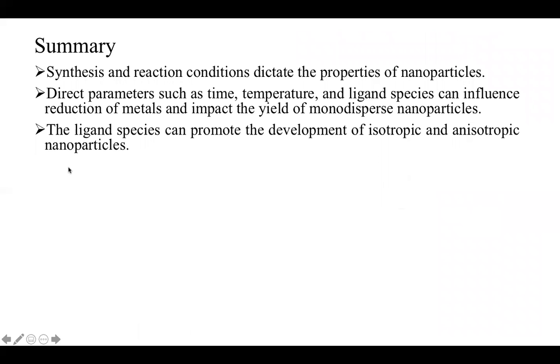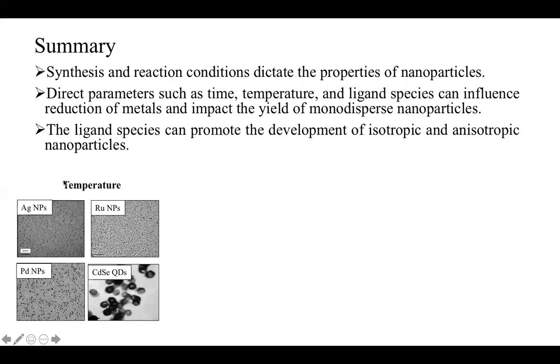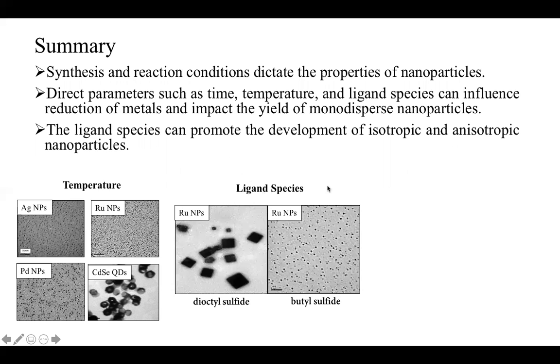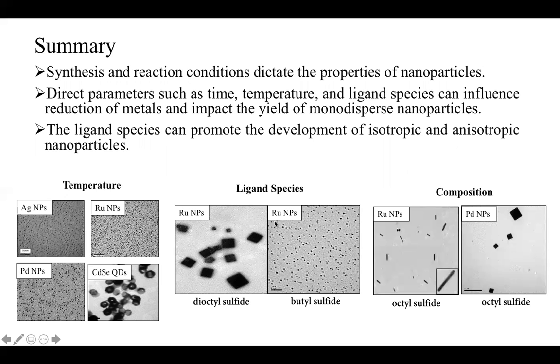So in summary, we were able to see that synthesis and reaction conditions dictate the properties of nanoparticles that we have, and they can be directly influenced based on our time, temperature, and ligand species, because these things directly impact the stability, the reduction of our metal, and our dispersity of shape. And these ligand species can also influence the nanoparticles that are formed. So again, based on temperature, we could see that we were able to have increased yields or different structures in the spherical shapes. We could also see that the ligand species influence how we had diversity in our shapes in the compositions. So from rods to cubes and spheres, we were able to produce in this method.